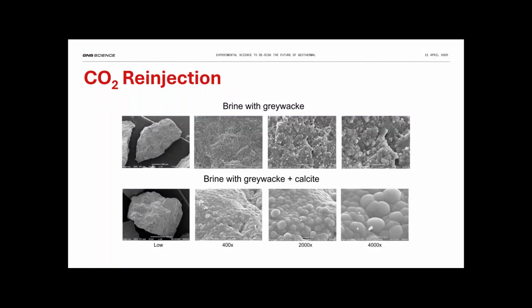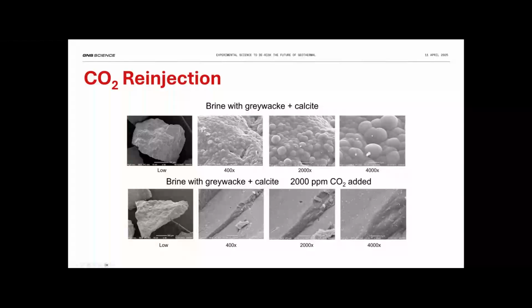So what's this got to do with CO2 reinjection? Well, the photos at the top here are the exact same photos as before when we had brine with calcite. So we can see again, there's quite a thick silica, but then we did the exact same thing. So this is brine with calcite, Wairakei with calcite, but then we added 0.2% carbon dioxide. So basically we're re-injecting CO2 now, and there's no silica scaling. So CO2 is actually a silica anti-scalant.